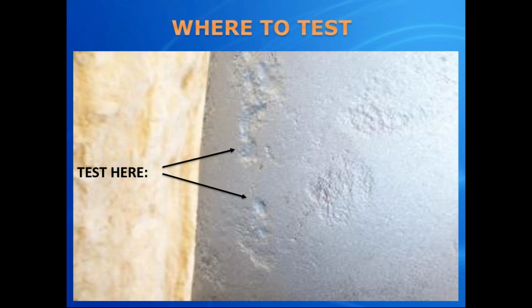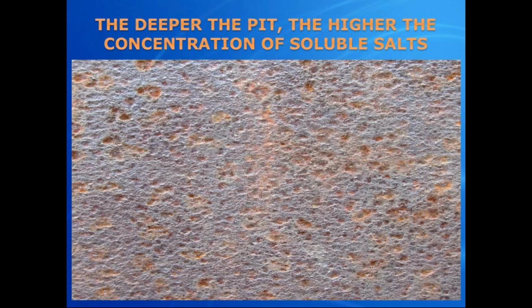This is a coating system that was removed and cleaned up to a near white metal blast, and you can see that there was a lot of pitted corrosion underneath this coating system. And if you were to test for chloride, sulfates, and nitrates, you don't really want to test up in these areas where my mouse is, but where the black arrows are, the heavier pitted areas is some of the better places where you want to test, because that's the most highly concentrated salt, no matter which type of salt you're looking for. You test in those areas, and then when you're doing a blasting operation, you'll test periodically, not as much, but you do test periodically, to ensure that you are removing the contaminants, and then you test afterwards in the same spots to make sure that you've removed those contaminants according to specification.